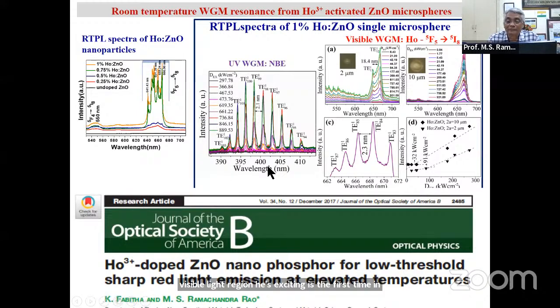And the very interesting thing is the lasing threshold for holmium doped zinc oxide is just 32 kilowatts per centimeter square, whereas in pure, undoped zinc oxide it's almost one order of magnitude more to get the lasing action. So you can make low power lasers in the visible range using doped zinc oxide microspheres. This is very exciting work.